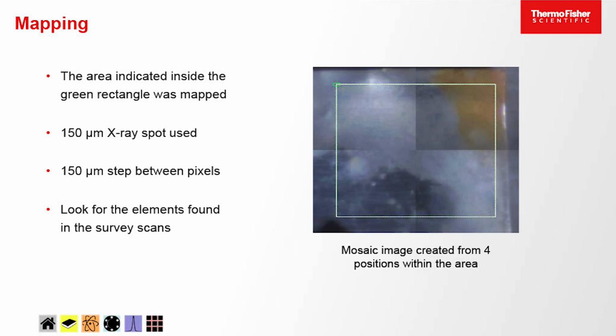If we do minutes per pixel, it's going to take days to collect the data. If it's seconds, then we're going to have the image in an hour or 2. And actually, this is quite an old example. The system here now has our new image acquisition mode we call SnapMap, where it can collect an image in a minute or 2. So it's an even much faster way of operating.